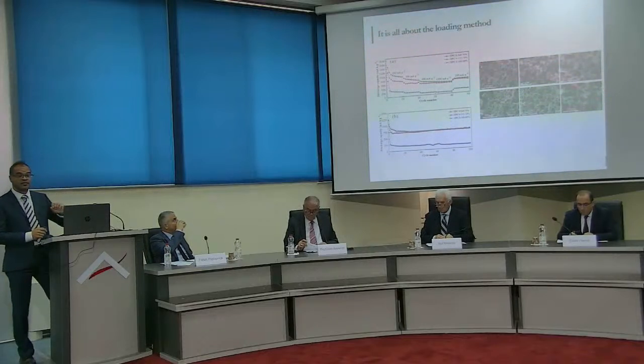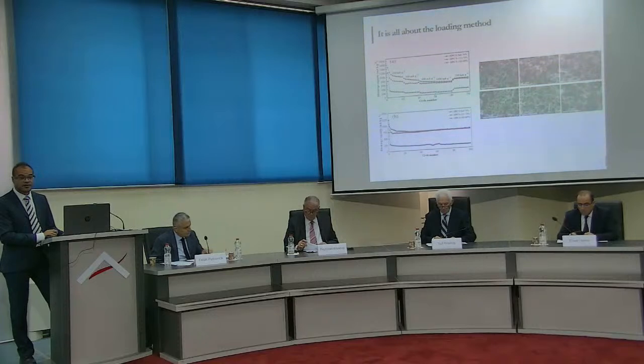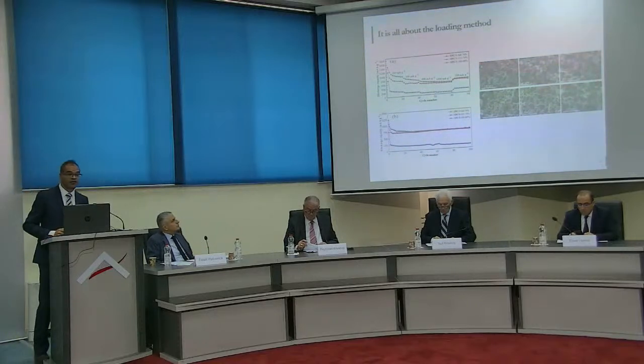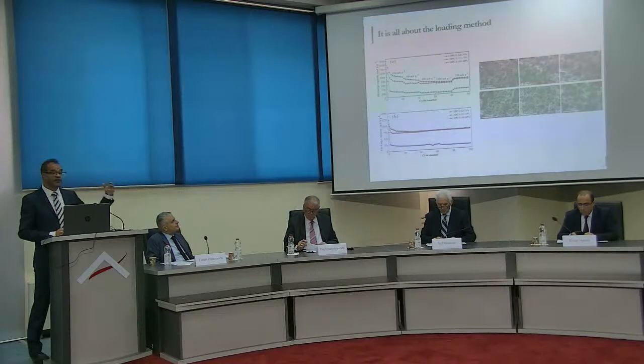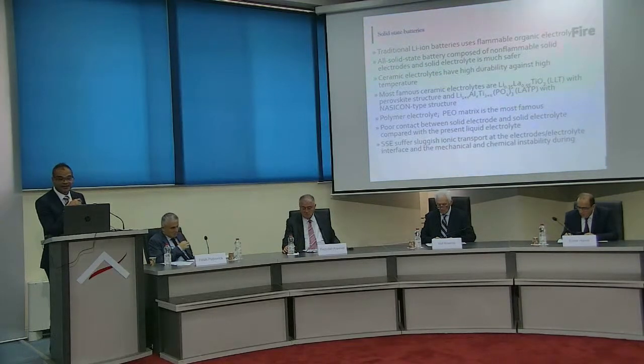So you can see the bottom one, the blue one, is actually the one loaded by just elemental sulfur directly impregnated into the sponge. And you can see it's actually the lowest of the performance, simply because it deposits on the surface only of the porous structure. But when we try to load this elemental sulfur from solutions, it goes deep inside the pores and nanopores of the sponge, giving obviously higher performance as well.